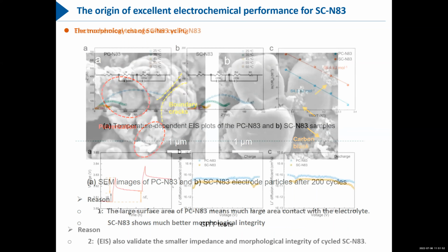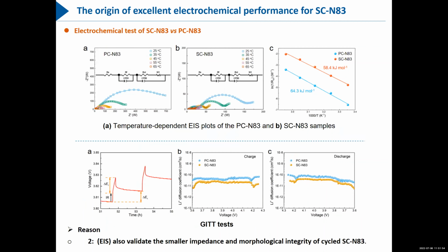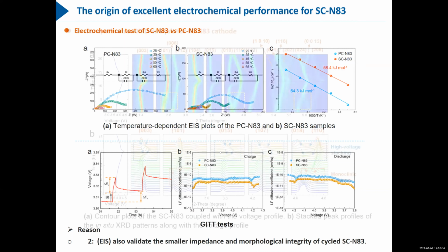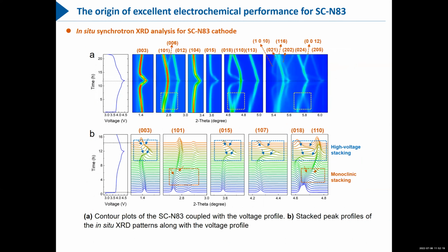We have also done some electrochemical tests like a GITT test and impedance test. This is just some normal electrochemical testing. We know that the single crystal shows a smaller impedance and better morphological integrity after cycling of these materials. And another part, a very interesting one, is that when we tried to study these materials, we used in situ XRD. We found a very, very interesting phenomenon, especially for this single crystal material.